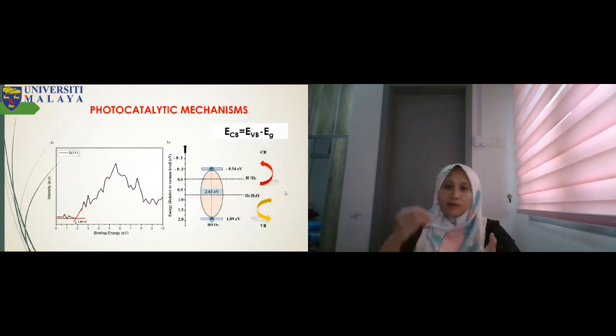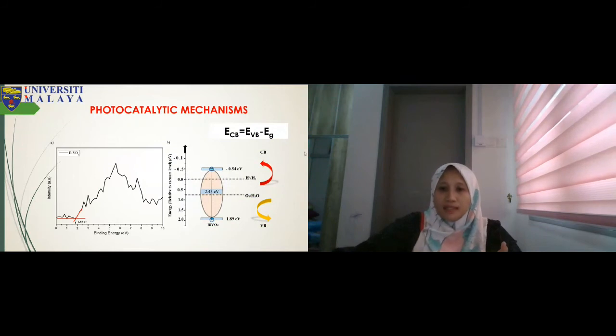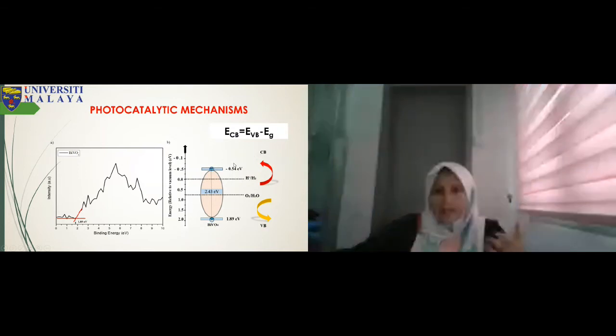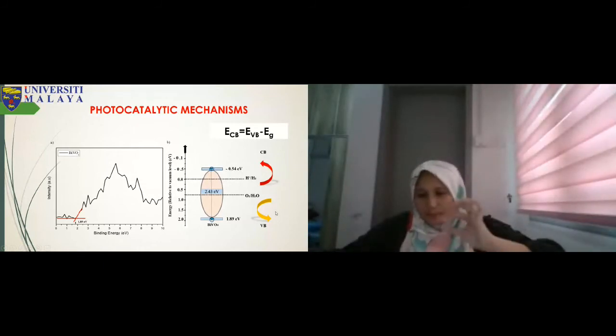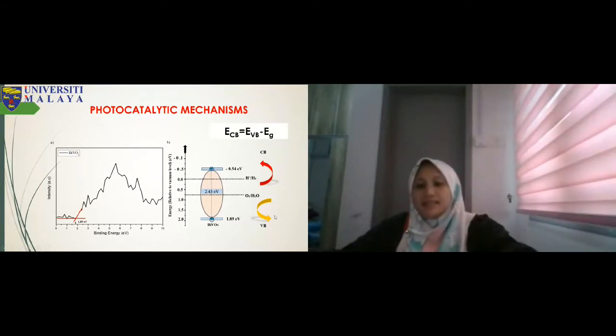We want to know the valence band. So for the VB, we get it from the analysis. For the XPS, we extrapolate here, and then for the band gap, we can create the band diagram. By a simple measure, the CB is around negative 0.54. So this is the photocatalytic mechanism.